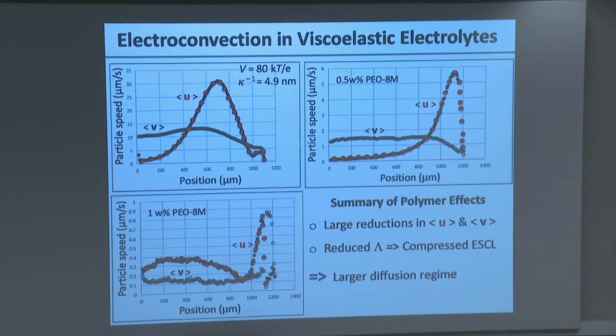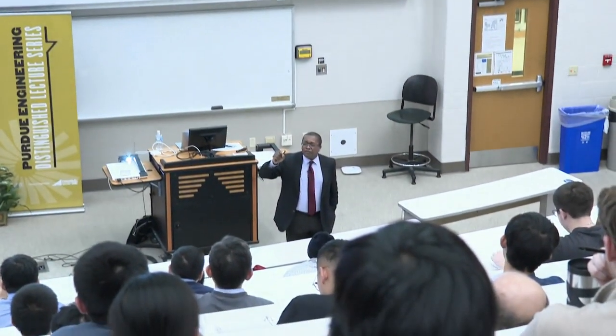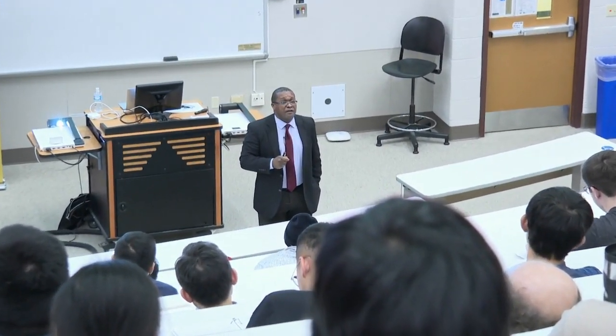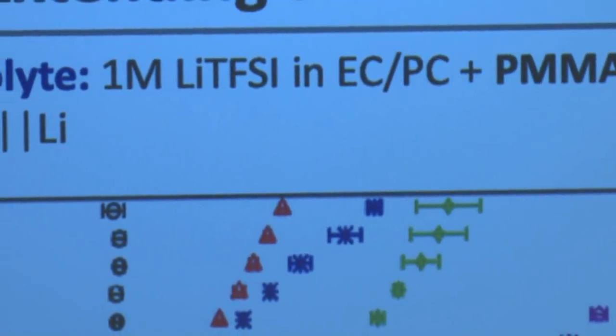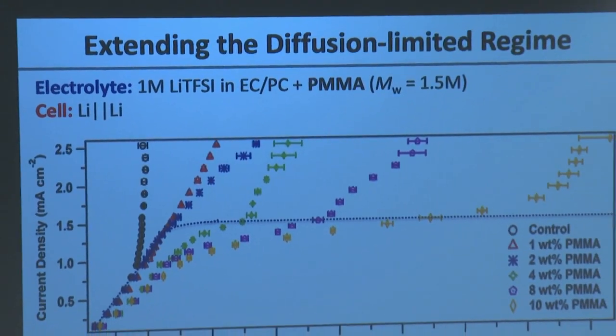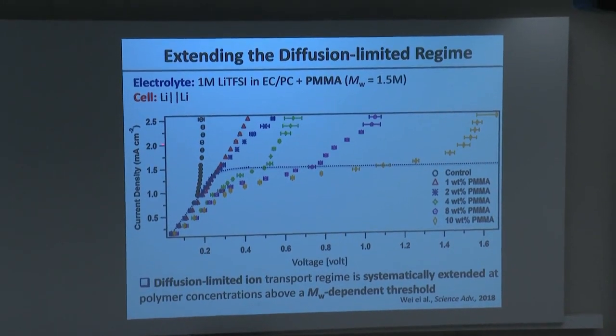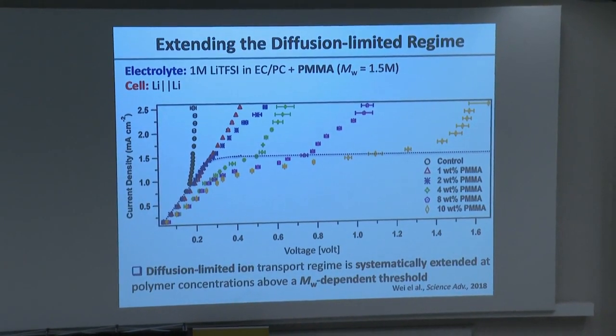But remember what started me along this line of attack was this experimental observation that in real systems, when I push the system above the diffusion limit, I get new flow, I get new current. And the question was, if this is true, that the polymer is able to slow down convection, which is the source of the new current, then it should be able to slow down the new current itself. And so we measured that. And this turns out to be a much easier measurement to make. So we basically measure the current, J versus V, in electrolytes that first had no polymer, were initially linear, and then they diverge. In this case, they don't even get to the limiting current. The flow is so strong, the convection is so strong. But as we add polymer, you see this kind of bending over of the curve. So you shift this region of upturn, this flow region, out to much higher voltages, indicating that you're able to stabilize the flow at any given voltage. So that was kind of nice.